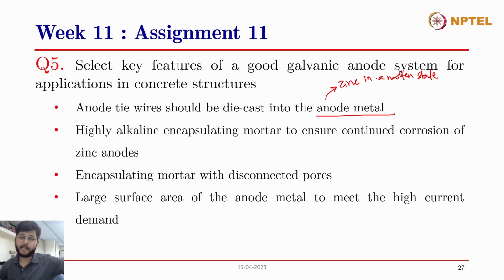So they should be die cast instead of welded, because if you weld those tie wires onto the anode metal, the welding metal might be different, and that will create problems in the anodic system, because if the metals are different, as we have also studied, that will create problems like selective corrosion or galvanic corrosion. If the welding metal is reactive in nature, then that will get corroded while the zinc will remain intact, and this will create problems.